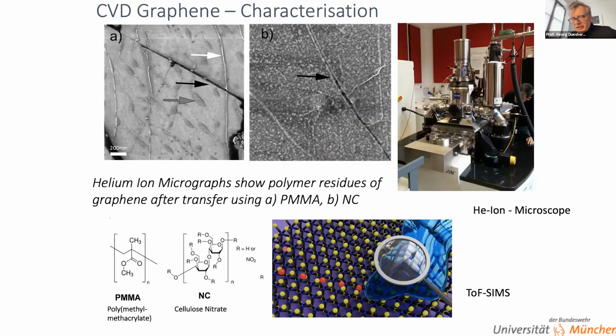But what I wanted to show you, and these are old images from a helium ion microscope we had in Dublin at the time, from various transfers. You end up actually with a material which is not that clean. And you can see that you have water bubbles underneath the graphene, you have ripples and rips, and then you have a lot of residues from your polymer transfers. This is cellulose nitrate here, which shows up in a helium ion microscope, but you wouldn't be able to see this in a normal SEM because the electrons wouldn't visualize it.